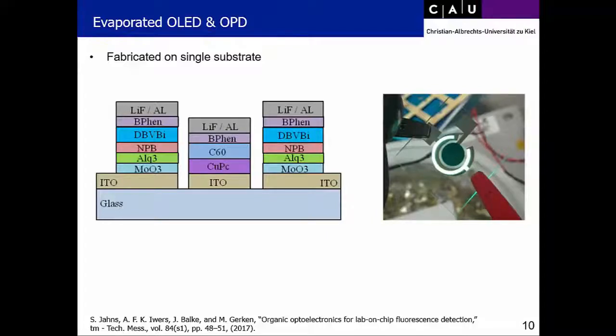In the second design, we evaporated on ITO electrodes, the ring as shown here, for the OLED material, which uses the DBVBi as the emitter material, which is blue-greenish, and then we had a detector here made up out of copper phthalocyanine and C60 as the detection material. And you can see now here the ring-shaped OLED and the OPD in the middle here.